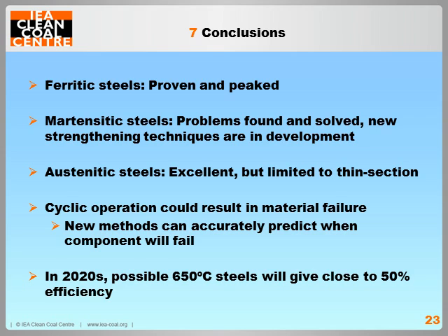So to conclude, ferritic steels are well proven and seem to have reached their limits. Martensitic steels are heavily used, problems have been found and solutions have been developed. Austenitic steels have performed well, but they are limited to thin section applications. Operating power plant beyond their design criteria, such as severe cyclic operation, could result in failure, which could be catastrophic failure. Consequently, new methods can accurately estimate when failures may occur, so preventative action can be taken to minimise financial losses. 650 steels could be commercially available in the late 2020s for net electrical efficiencies reaching 50% on an LHV basis in some cases.